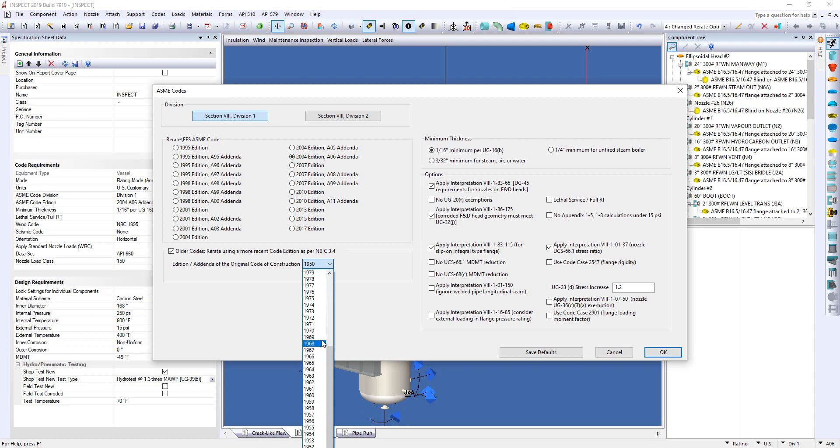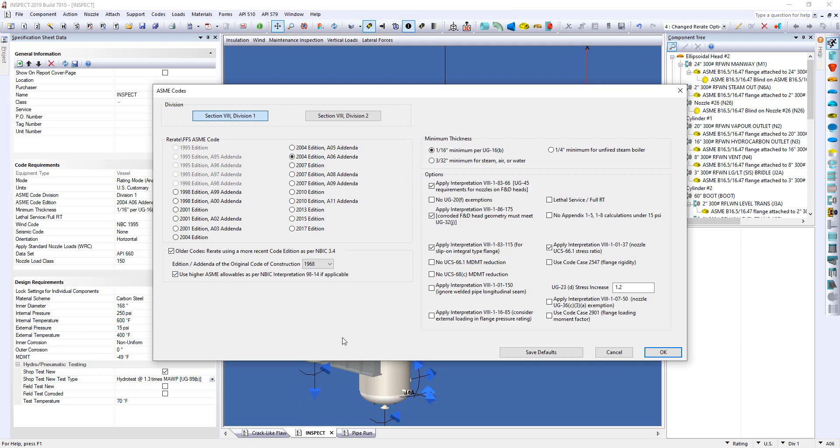Okay, that's a key year when we're looking at it. And there is actually an option that presents itself for using higher allowable, ASME allowables, per NBIC interpretation 89-14, if applicable. So, if applicable, what does that mean? So what we're going to do, this is going to be three checks. We're going to make sure that the MDMT based on design pressure is adequate, the vessel is not operating in the creep range, and is not in lethal service. Now, if you meet all three of those checks, Inspect will use the 3.5 design margin to give you the higher allowable stress. If it fails any of those checks, or if you select a year before 1968, Inspect will use the pre-1999 allowable stress based on the 4.0 design margin.